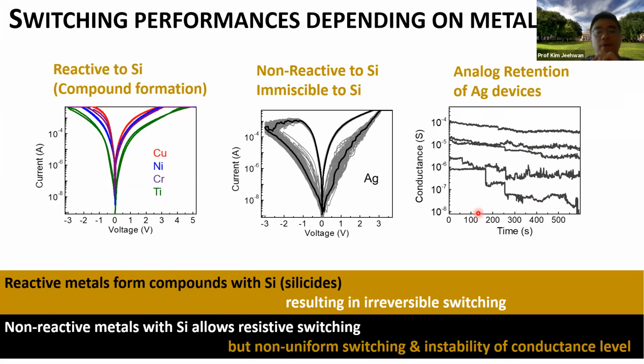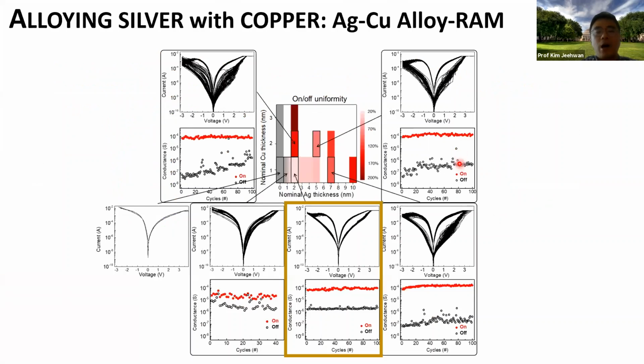This is the switching behavior of the silicon memory with the different metals. As you can easily imagine, if you use a compound formation metal, there's no switching at all, because copper, nickel, chrome, Ti form a very stable silicide. Once it's formed, it cannot be reset because it's very stable. So this is not going to be the solution. Then if you use silver, you have switching, but unstable and very unreliable switching. At the same time, with silver, as you can see, the long-term memory is not secured in multiple weight levels. So now we try to find the right copper content to make an impact.